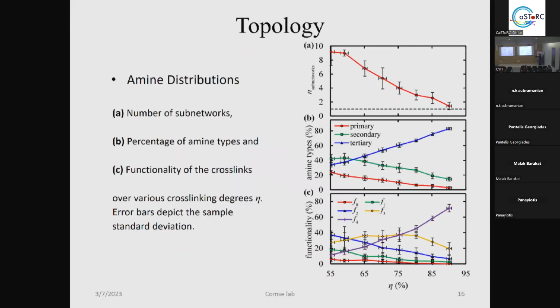After that, we saw the topology and how the subnetworks and the functionality change as the cross-linking degree increases. We can see that the subnetworks, as we expect, decrease, because we have a fully glassy system as the cross-linking happens, and thus the subnetworks become fewer and fewer because we have smaller groups that are attached to each other.